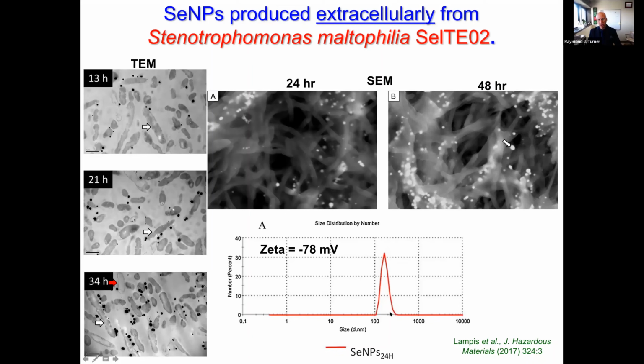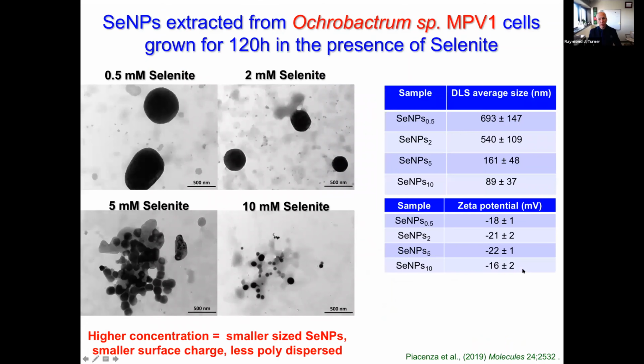We have still a good, very good size distribution and a good stability size. So this is just scanning electron microscopy versus transmission to identify the material that's being produced extracellularly. Here with this one, we're trying to play with the size of the material. Usually for a chemist, we can play with size by the initial salt of the metal that we're adding. Here we see that as we increase the metal load, we actually got smaller particles. So we were able to control the size by simply changing the concentration, with all the other parameters the same. And all of these had about the same zeta potential stability.